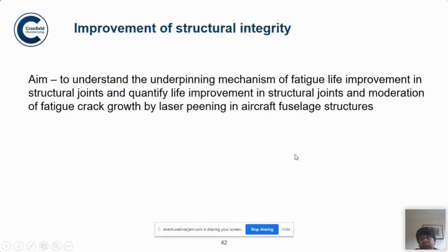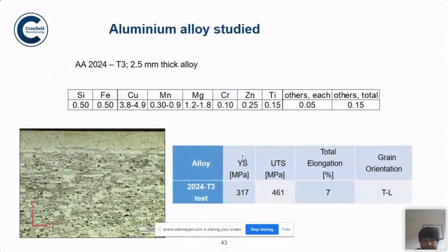So this particular project, we worked on an Airbus component, which is a fuselage, and we tried to resist fatigue crack growth by laser peening. The alloy was aluminum 2024 T351, which is a very standard alloy. And you can see here the grain structure, and on the top the clad layer of aluminum.